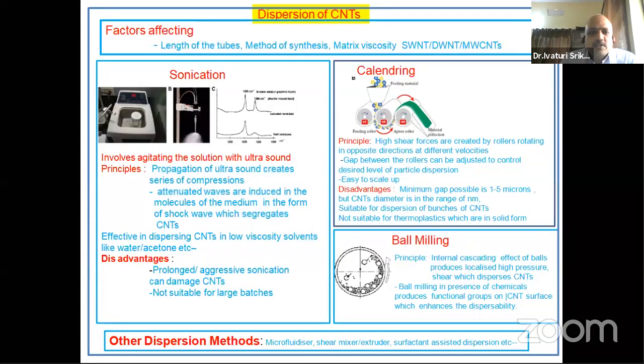So this is one thing. Then, coming to the dispersion, there are different dispersion methods people have tried. One is sonication. You take the CNTs, mix them into the resin system, then sonicate it. Sonication uses a probe. This is a sonic probe. And you can dip the sonic probe into a resin bath and then apply sonic force. The sonic waves, as they are traveling, create a series of vibrations in the matrix that is dispersed with the CNTs. And as it is creating vibrations, there will be some shear forces that will be assumed by the bunch of CNTs, and that results in dispersion of CNTs.